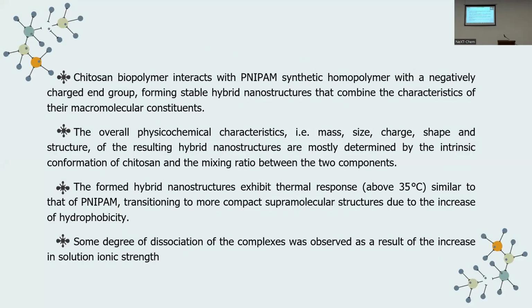So in conclusion, chitosan biopolymer interacts with PNIPAM synthetic homopolymer, which has a negatively charged end group, forming stable hybrid nanostructures that combine the characteristics of their macromolecular constituents. The overall physicochemical characteristics, like mass, size, charge, shape, and structure of the resulting hybrid nanostructure, are mostly determined by the intrinsic conformation of chitosan and the mixing ratio between the two components.